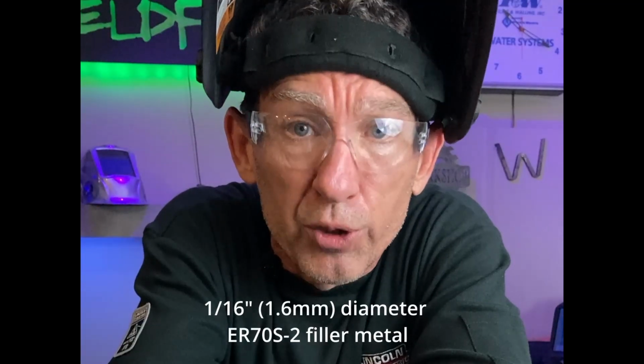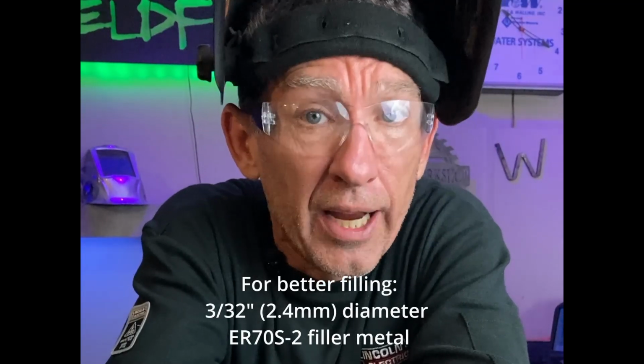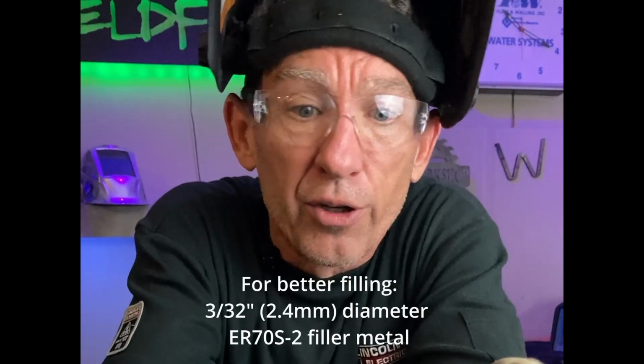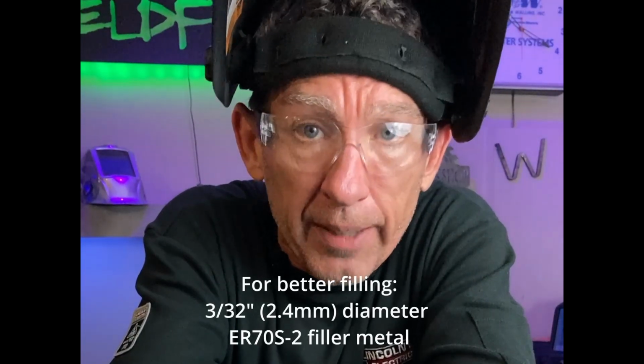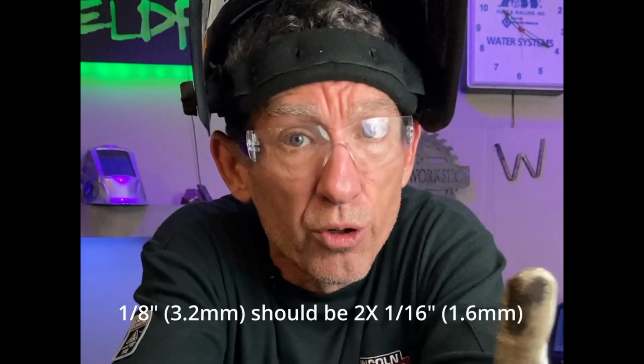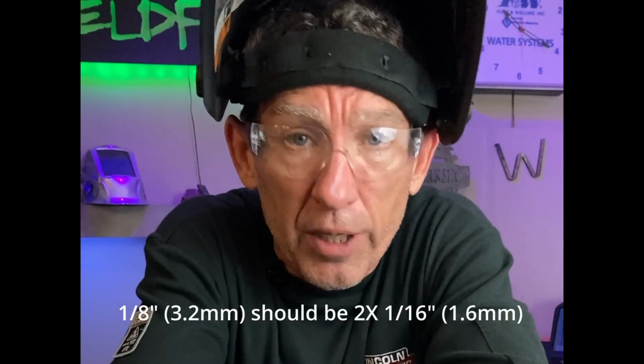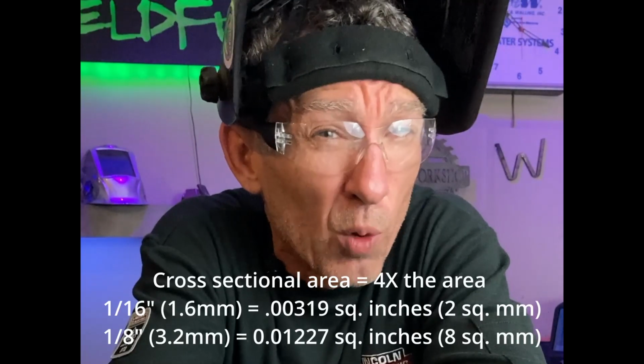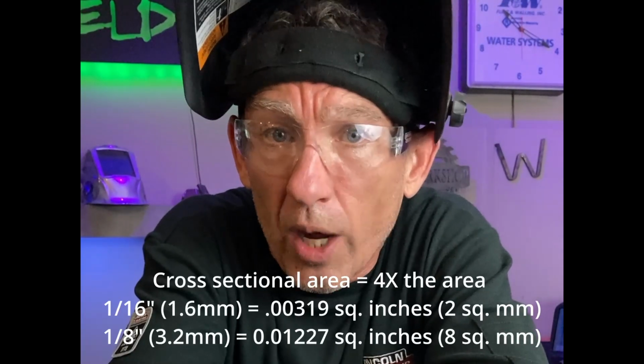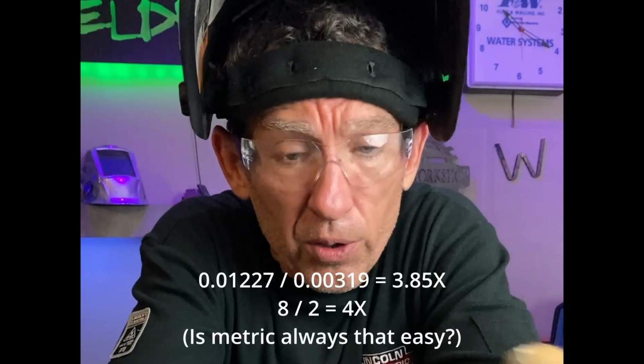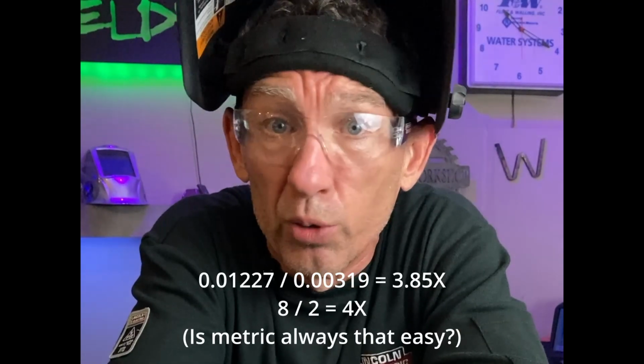If you jump up to a 3/32 filler rod, you're going to have to dip less, and you may find that you get a little bit better filling. Just a caution there, though. When you go up with filler metal diameter, especially on steel and stainless, it takes a lot more energy to melt that rod. That's why with these materials, I try to use a 1/16 filler rod. On the other hand, if you switch over to aluminum, aluminum's such a good conductor of heat. I rarely use 1/16 aluminum rod because it melts before it gets to the puddle.